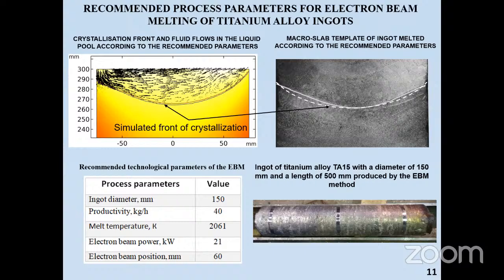On slide 11, a macro slice of the ingot is presented. A comparison of the calculated crystallization front and the crystallization front of the ingot itself, indicated by the dashed line, indicates a good match between the profile of the front and the result of mathematical modeling. The macro slice is characterized by the absence of shell and discontinuities. The ingot macrostructure has close equiaxed crystals, which is an indication of good ingot quality.